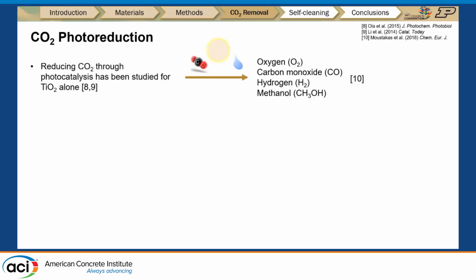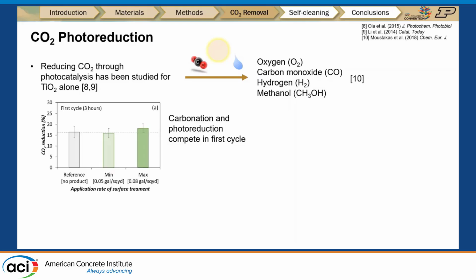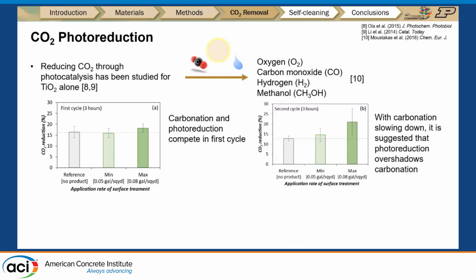Carbon dioxide photoreduction has been studied with titanium dioxide for a long time. It says that in the presence of sunlight and water, carbon dioxide will be converted into oxygen, carbon monoxide, hydrogen, and methanol. In our first cycle, we see that the carbonation is actually competing with the photoreduction activities. But in the second cycle, with the carbonation slowing down, it is suggested that the photoreduction starts to overshadow the carbonation.